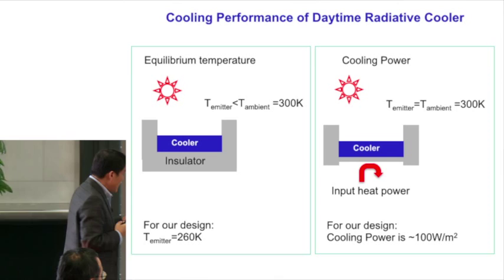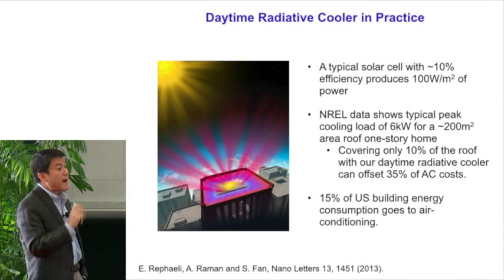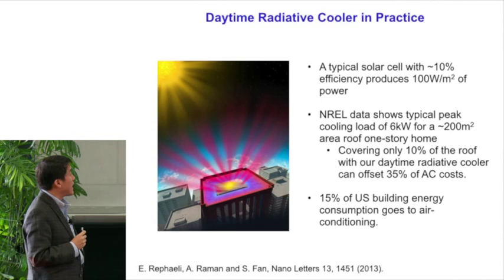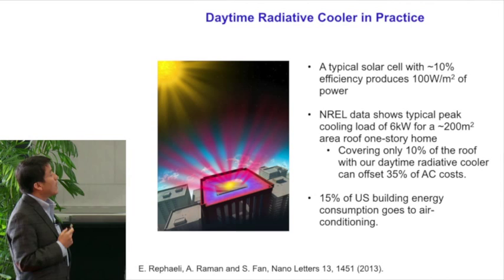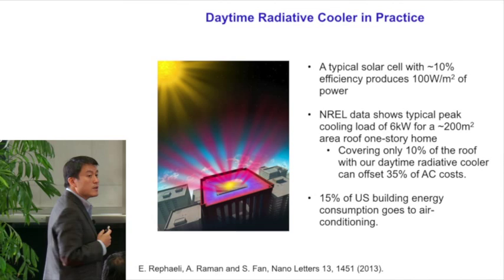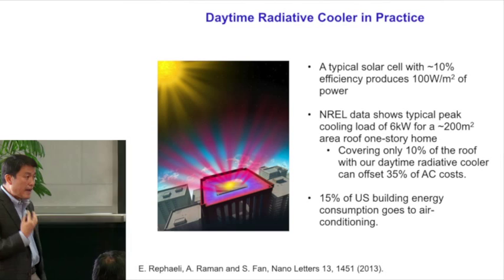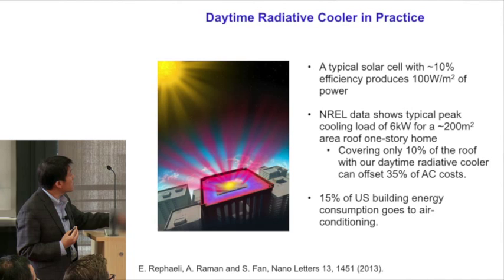100 watts per meter squared, of course, is a non-trivial amount of power. Order of magnitude-wise, this is where solar power sits, and there's a good thermodynamic reason for that. From a more practical point of view, a significant portion of US energy consumption in buildings, about 15% or so, goes into air conditioning. So being able to cut that down with this kind of radiative cooling technique can actually make an impact on global energy consumption. Motivated by the theoretical work, we then set out to do some experimental demonstration.